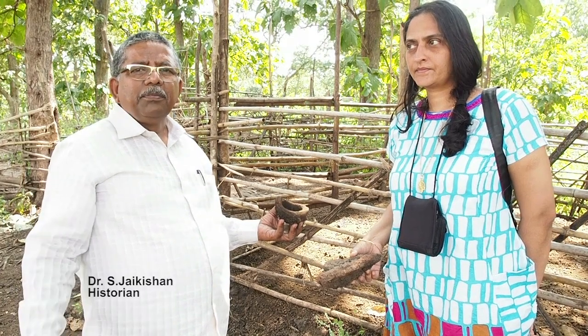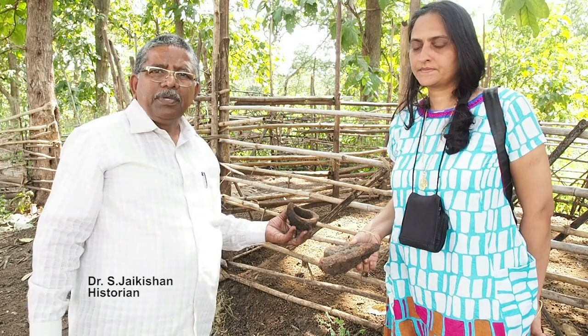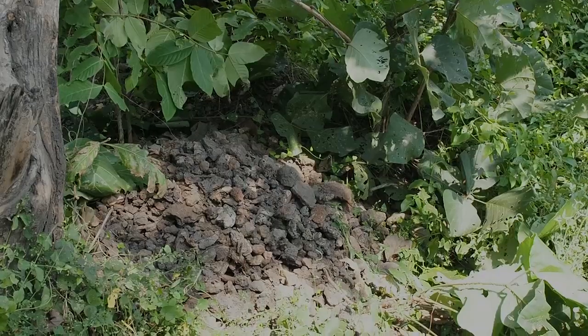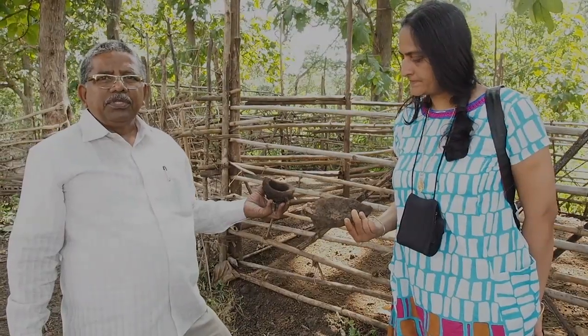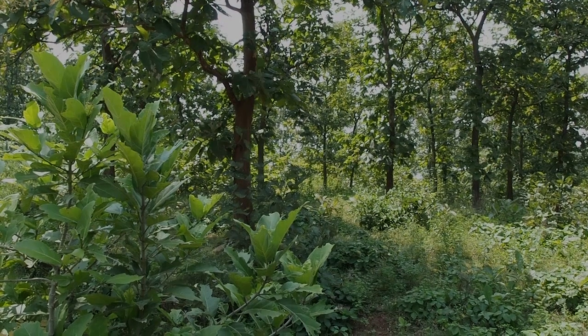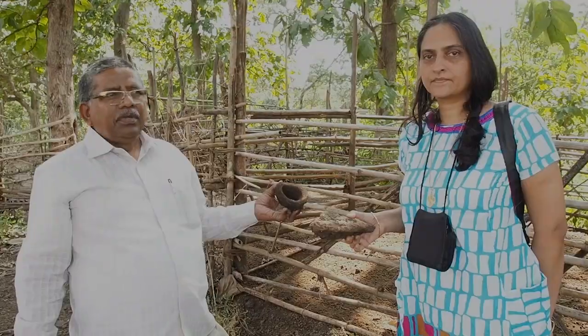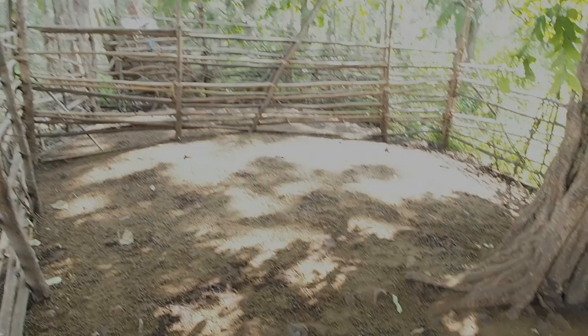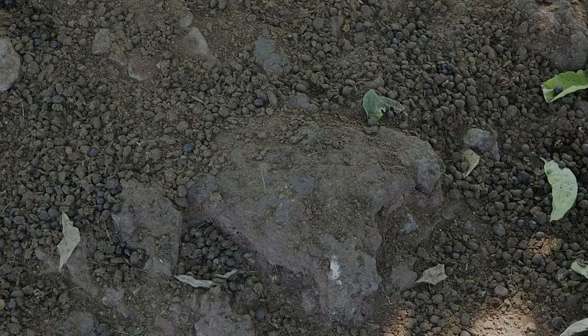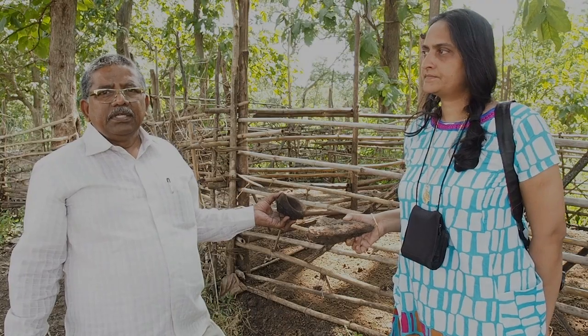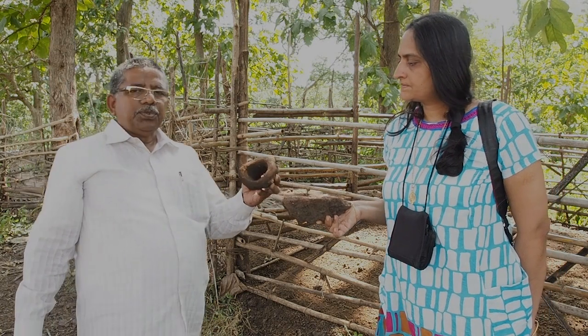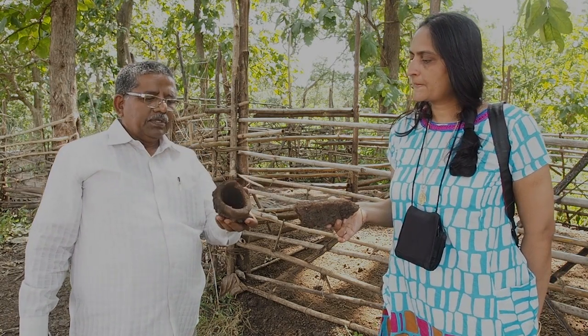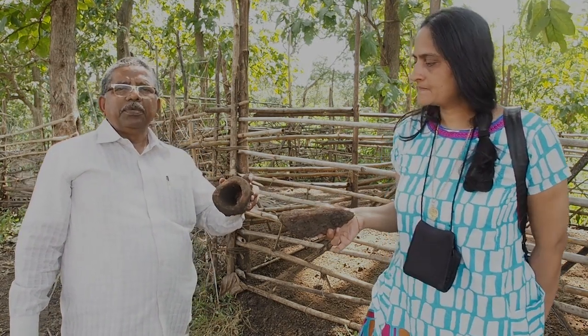Kadam is a very famous smelting site. Not only iron smelting sites, but there are several crucible sites. Individual heaps you can count in the forest of Kalleda may go more than 2,000 to 4,000 heaps. This is one of the big heaps here, adjacent to the village in the forest. Now we found this tuyere, which was used in an iron smelting furnace.